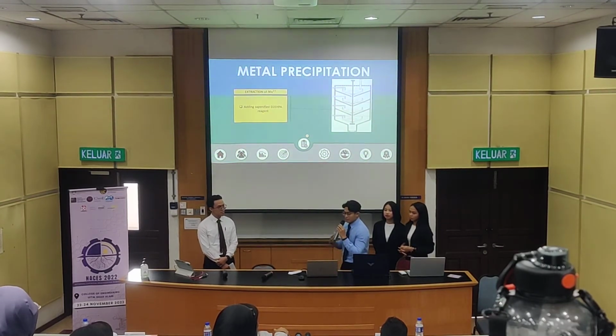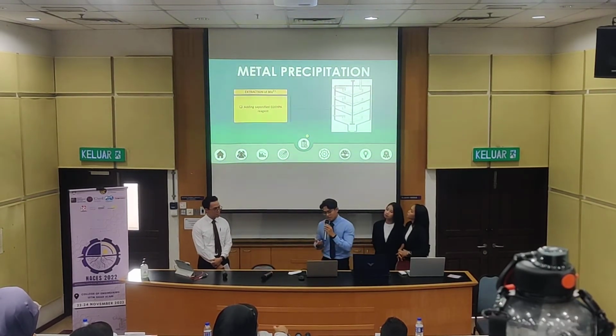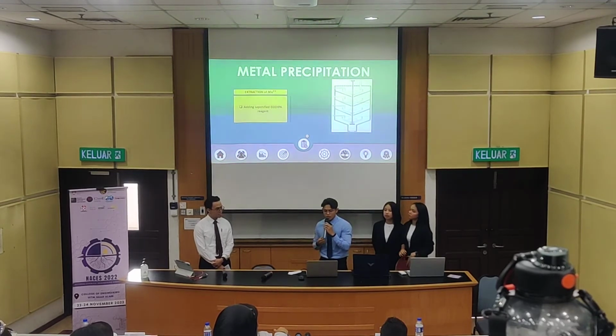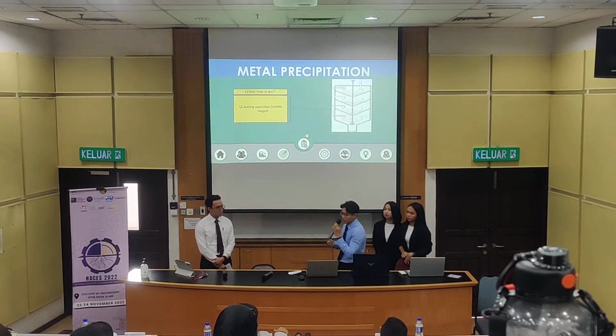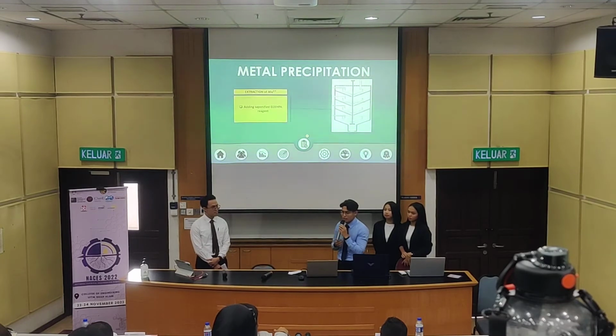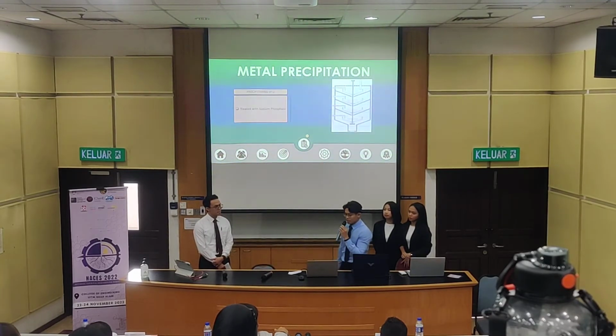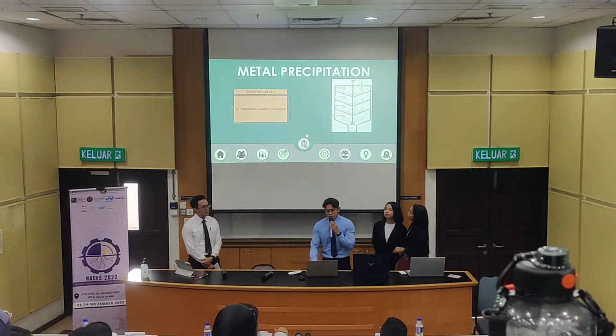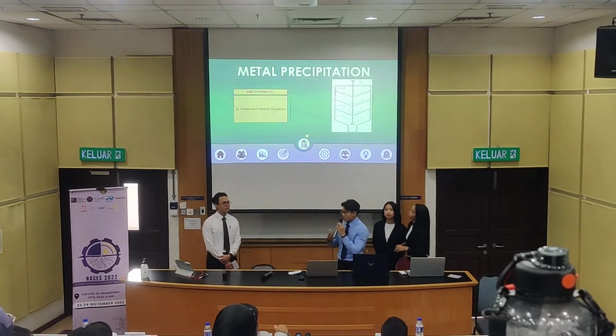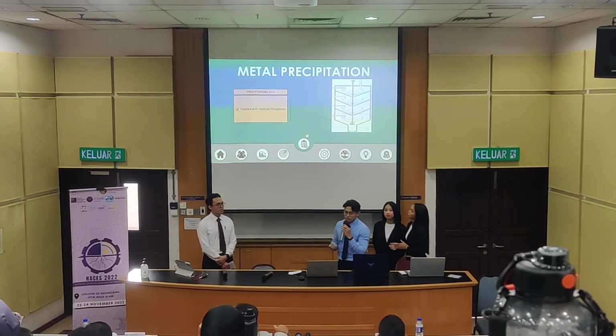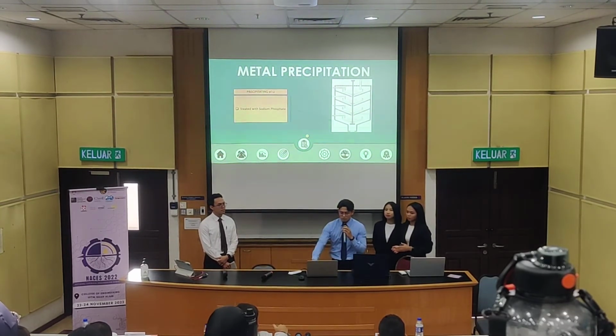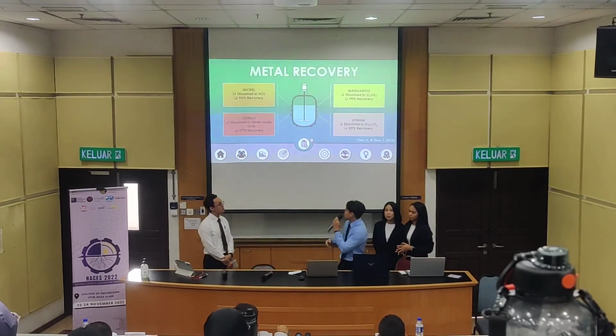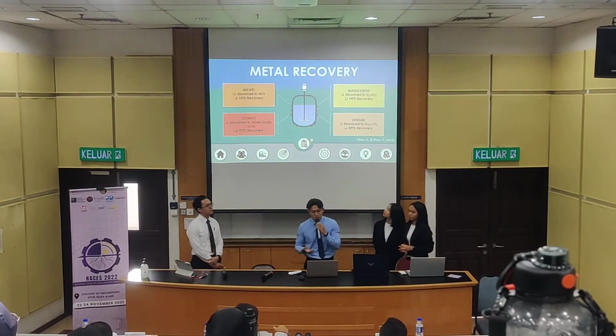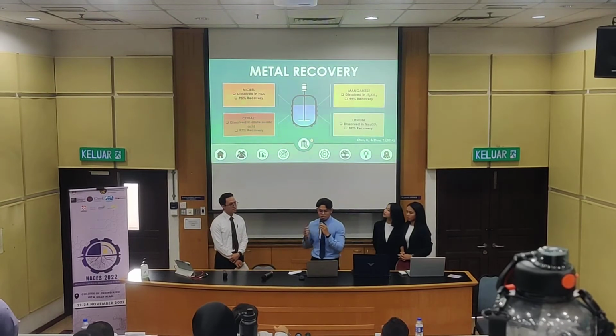Then, followed by the third stage, the precipitation of magnesium ion will take place by the addition of saponified diethylhexyl phosphoric acid. And last but not least, the last metal, which is lithium, will precipitate by reacting with sodium phosphate solution. After all the metals have been precipitated, it will go through the metal recovery process.